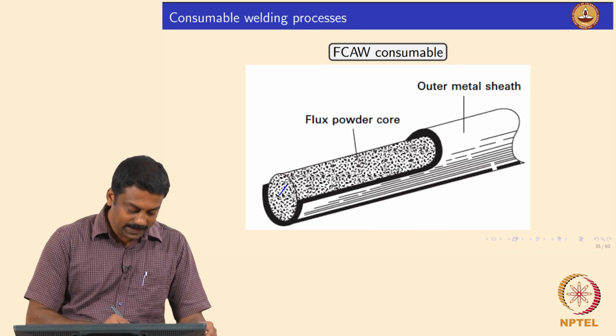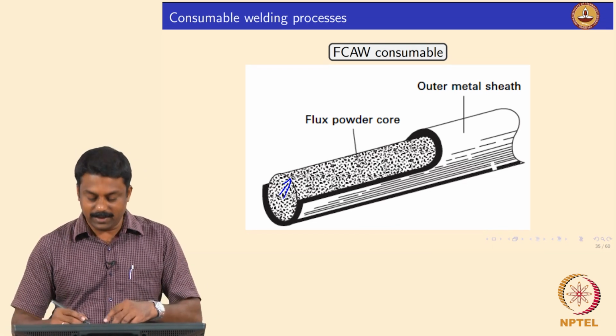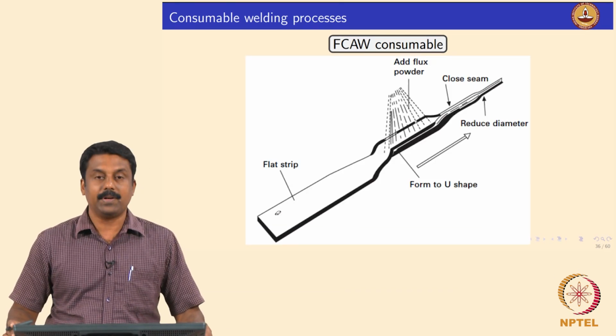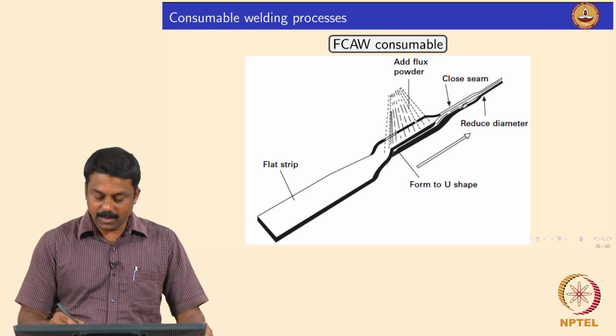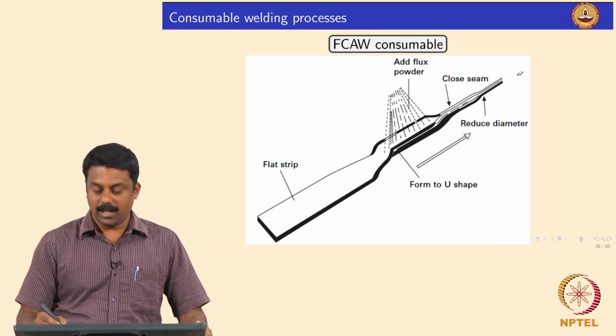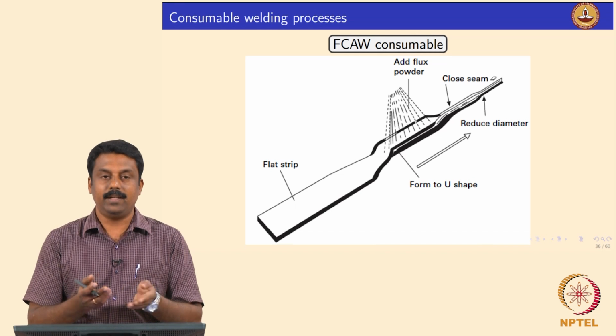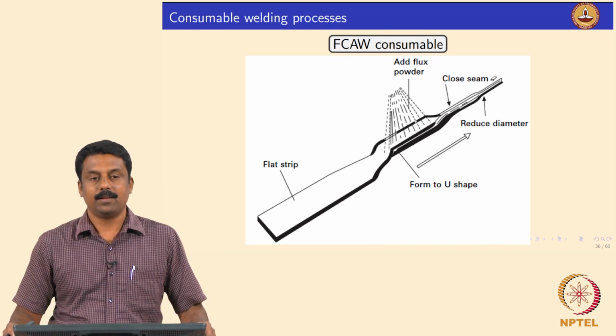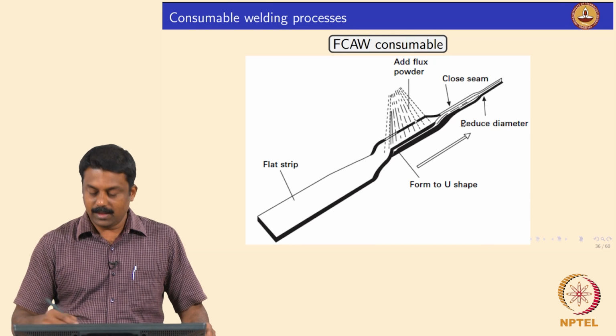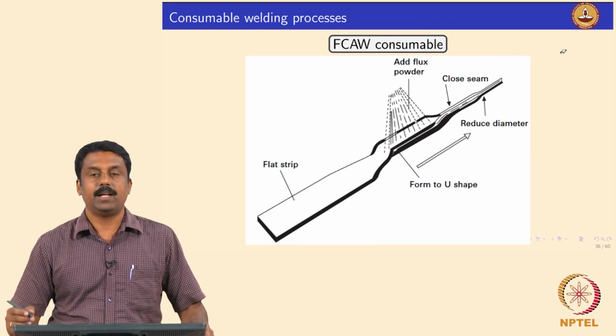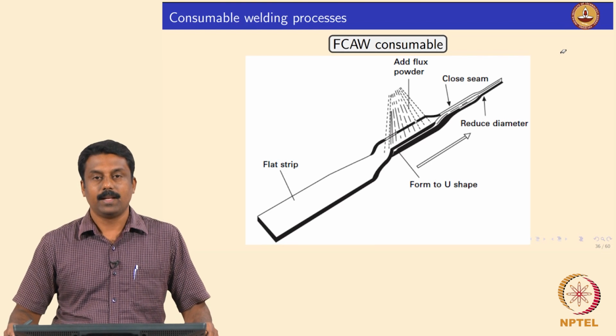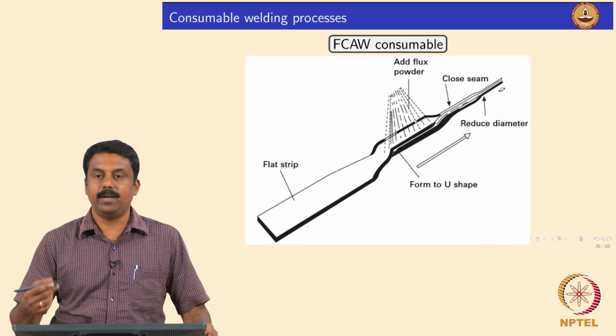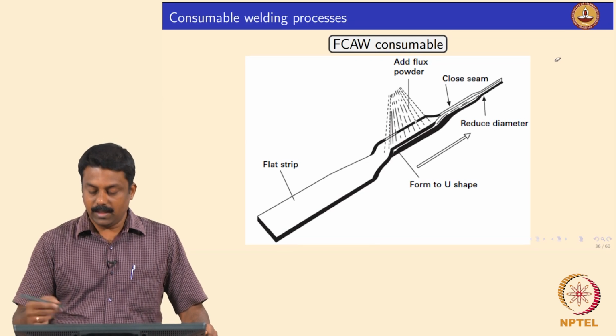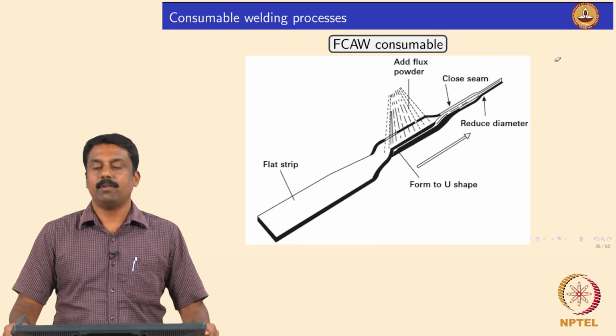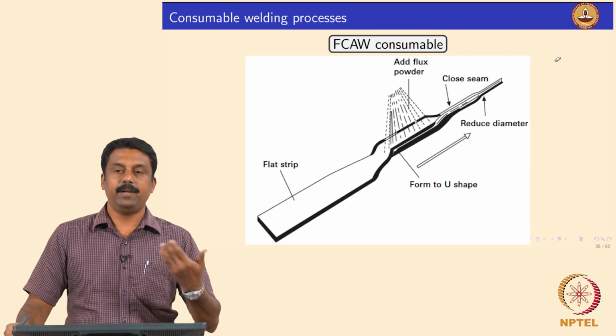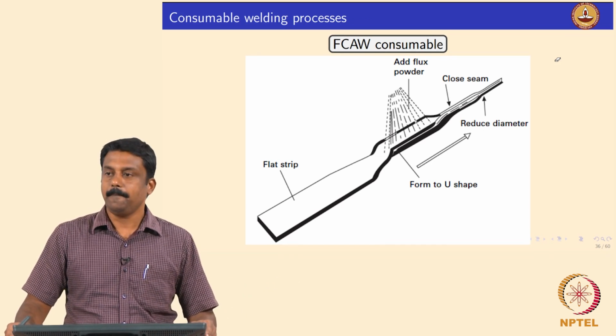So, all the compounds or the flux are added inside, and the electrode is made from a flat strip, and then you add the flux powder, and then you close it, and in most cases it is not really welded, it is just simple folding, right. So, they just fold it and then they close the seam, and you can generate as much length as possible, and then generally we make it similar to the GMAW electrode filler. So, we will have spools of electrodes made with varying weights and lengths, and that can be fed into the power source. Yes, it is clear.